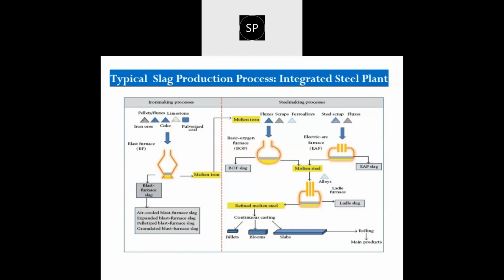In a similar fashion, there is another version of furnace called the electric arc furnace. The major difference between the basic oxygen furnace and the electric arc furnace is the method through which the arc is inserted inside the furnace. Through three electrodes, the arc is inserted inside the furnace in the electric arc furnace process. And in this furnace, along with the hot metal, we can put 40 to 50% steel scrap, which is not possible in the case of a basic oxygen furnace.